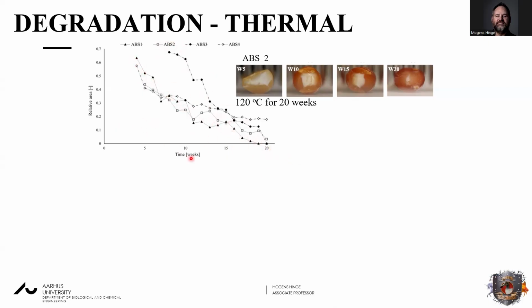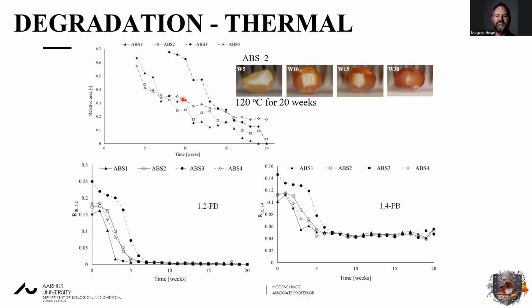So over the course of 20 weeks, we actually degrade the material and return all the way down here where it's almost only brown. There is a bit of difference between vendors, and that could be due to different amounts and different types of additive or different type of stabilizing properties. So it could be that you have maybe here vendor number 3, that they have added a bit more antioxidant or other additive to it that will ensure that it maintains more or less the same, but then when it's consumed, then it also just degrades. So in this way, we're just shifting the time scale a little bit. But let's look into the IR.